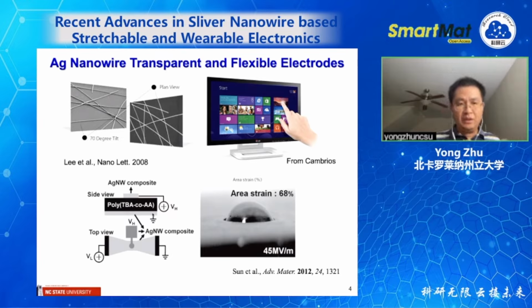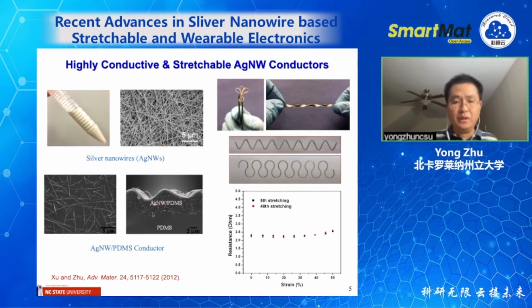Mostly the silver nanowires were used as transparent or flexible electrodes. I think our group was among the first to use this to develop silver nanowire based highly conductive and highly stretchable conductors, around 2012. So the method is very simple.